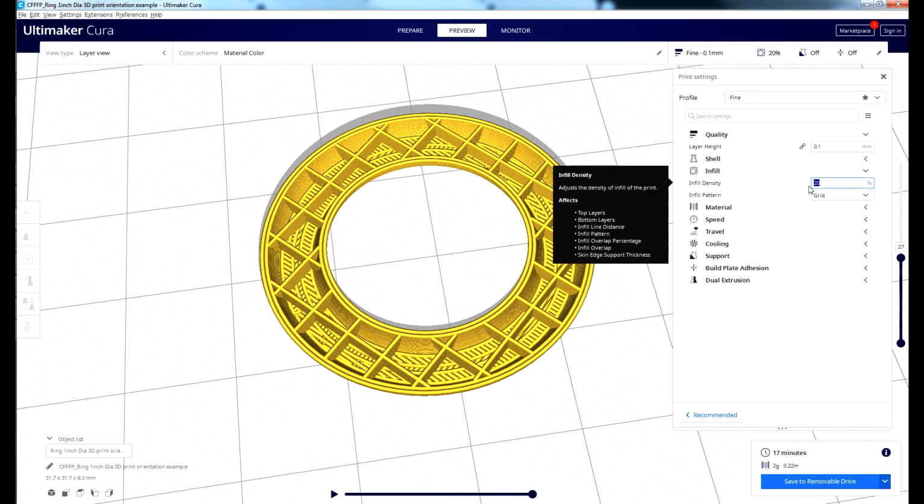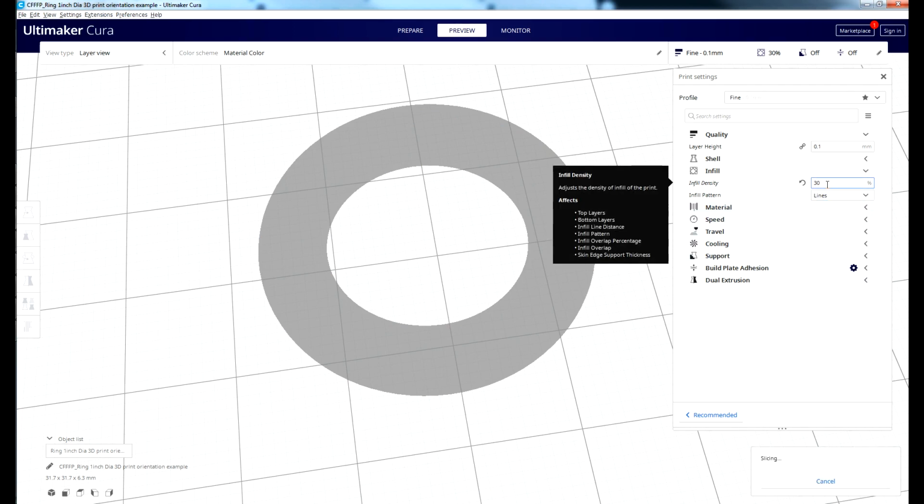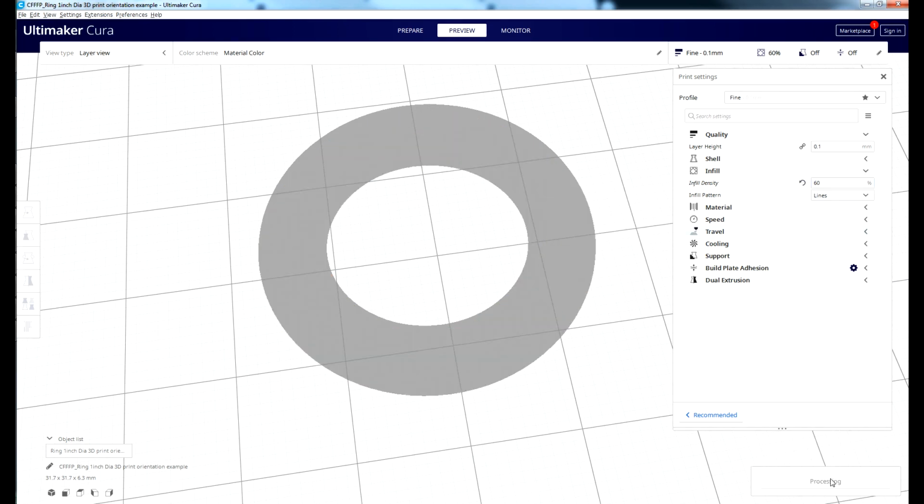The more infill, the longer the part takes to print, and the more material that's consumed. Infill is the density across the entire part. Generally, a greater infill will improve the overall strength characteristics of your part. However, this benefit will start to plateau around 75% infill and up.